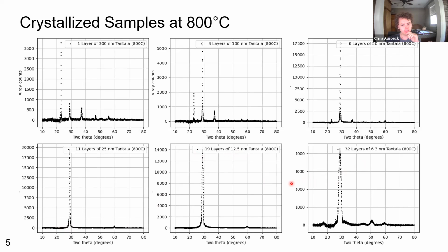You may also notice that for the 29-degree peak, as you get to smaller layers, the peak actually gets wider. And we can actually use the width of this peak to determine the crystal size. Usually the wider the peak is, the smaller the crystal size is.